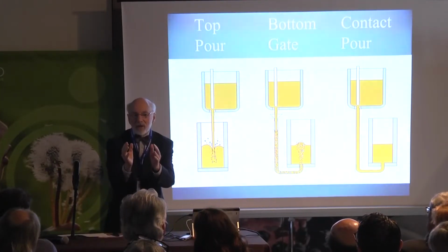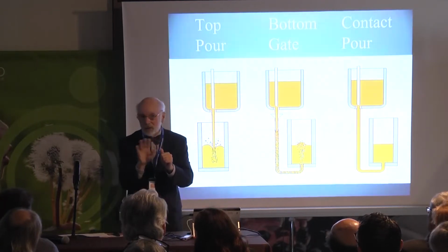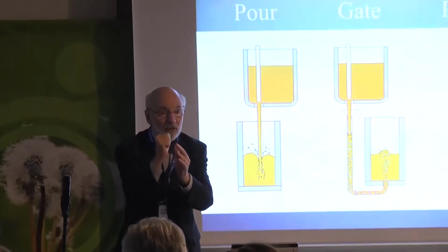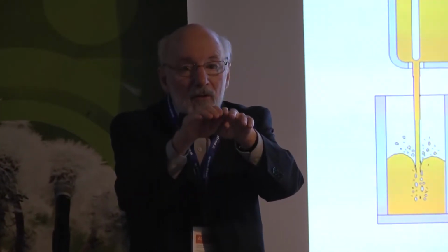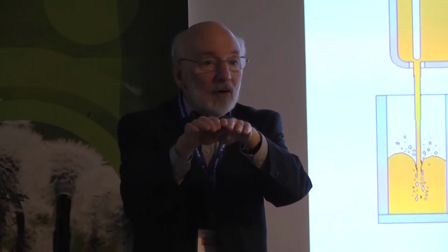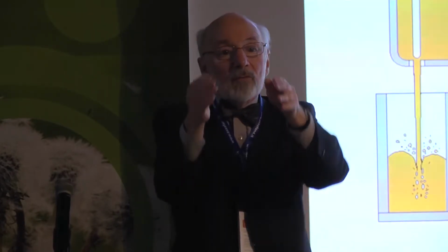And now the question is, how does it rise? That's not straightforward. It can only rise if it has enough buoyancy force to break the oxide, and so as the oxide splits and moves, the bubble can move up a little, but immediately the oxide reforms. And so it splits and reforms, splits and reforms.